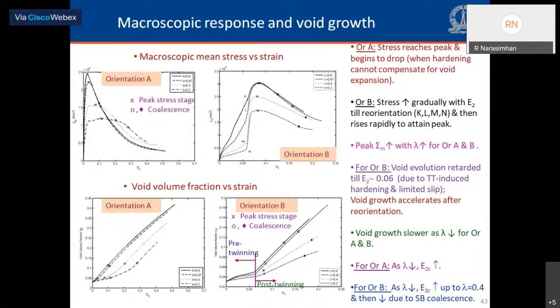Okay, now these are line plots of the macroscopic mean stress and void volume fraction corresponding to orientation A and B. In the case of orientation A, the macroscopic mean stress develops very similar to isotropic plastic solids. So if you look at the left side plot, the macroscopic mean stress in the cell increases very rapidly, and then the hardening in the cell is no longer able to compensate for the rapid expansion of the void, it reaches a peak, and then the mean stress begins to drop. And that mean stress peak value, as you can see in the various line plots, it decreases with the decrease in lambda.